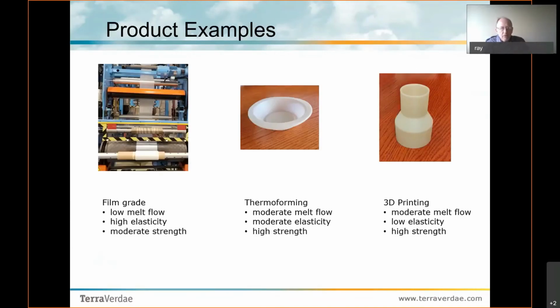So just some examples of what we accomplished. The picture on the left is a pilot scale blown film line. The film grade resin has, in relative terms, a lower melt flow index. It has high elasticity and moderate strength requirements. We were able to make cast film, much thicker cast films successfully, that you can thermoform into various pieces. It's just an example of a bowl, a tray. And so this material has a moderate melt flow and elasticity, but we designed it with higher strength.